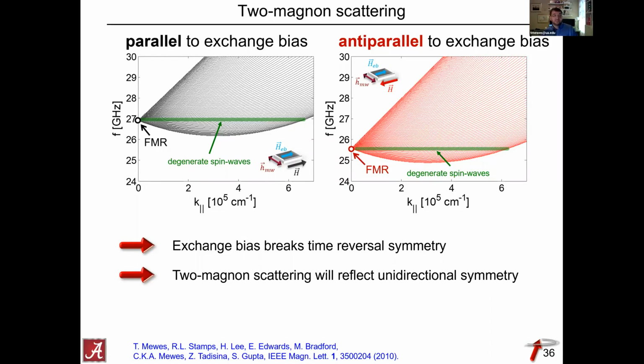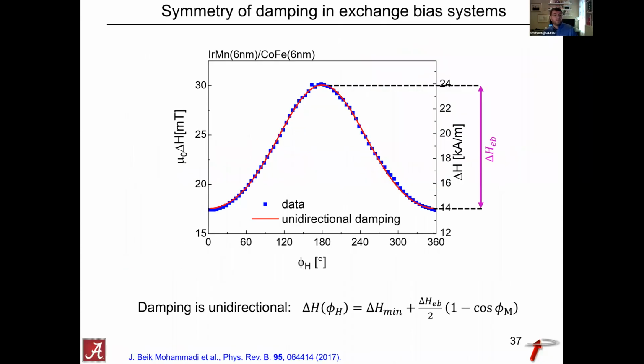And in order to at least get a sense of whether this is all that's going on in this system, we need to do a little better in terms of trying to map the symmetry of the system. So what we do here is, at a fixed frequency, we look at the angular dependence of the line widths. And you get this nice cosine dependence of the line widths at a fixed frequency. And you can come up with a model that essentially includes now a unidirectional term that reflects the symmetry of the system. And with that, you can now parameterize this unidirectional contribution to the line widths.